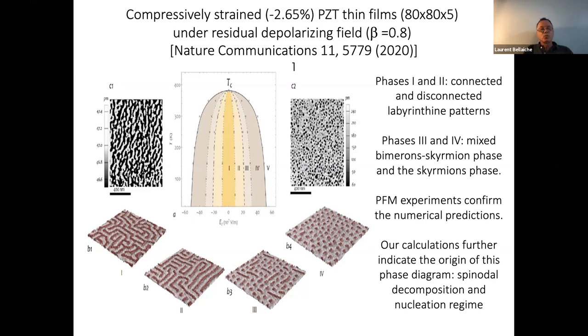For example, you have phase one. Phase one is a labyrinth structure. Phase two is a disconnected labyrinth structure. Phase three is a special bimeron skyrmion phase. Phase four is the special electrical skyrmions. And if you look at panels C1 and C2, these are experimental data that confirm the existence of these different phases. So with effective Hamiltonian, you can reproduce these nice, very complex topological phases. And you can also understand how they are created.